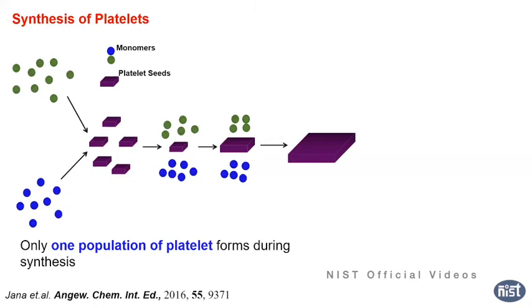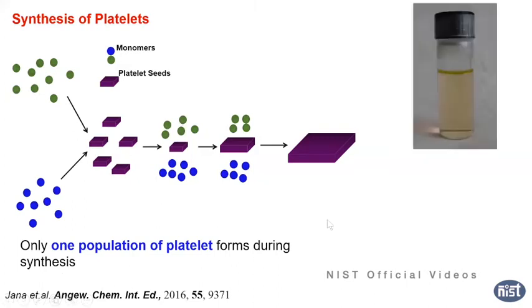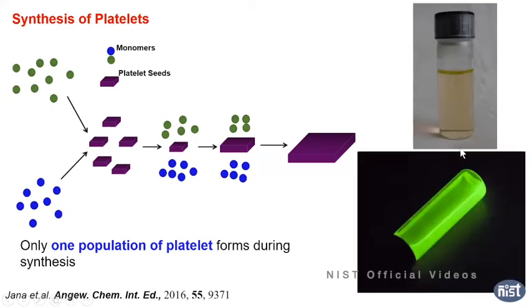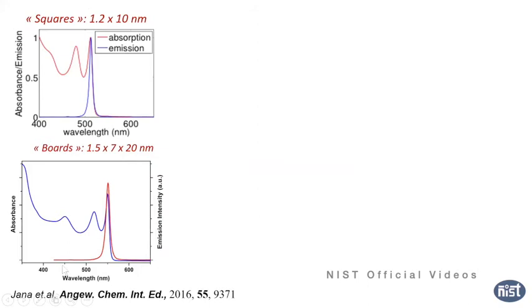And how we synthesize: we generally use 2 different kinds of precursors, and it grows a small platelet, and then you can grow it in one direction. The solution looks like this. You can see it's very transparent. There is only a light color, but it's very bright. Under UV light, you can see a strong green emission, and this is the absorbance and emission spectrum. You can see the emission is very sharp, like atomic-like emission.